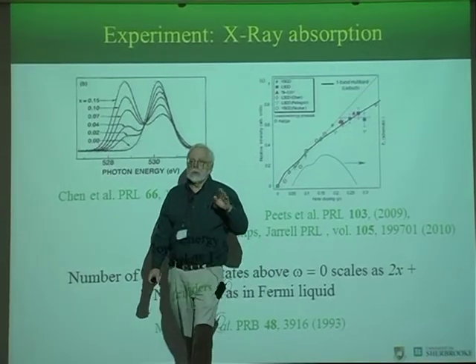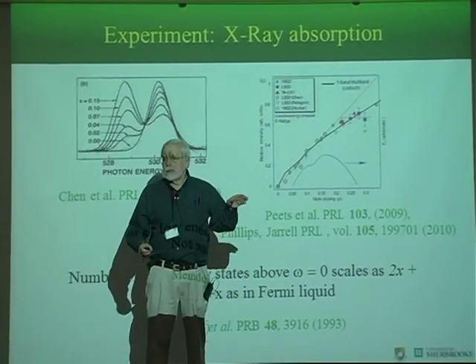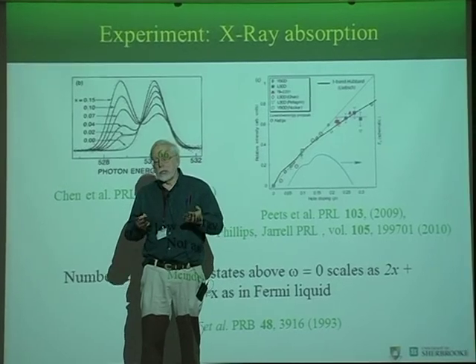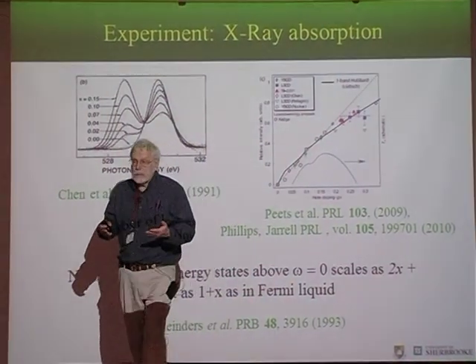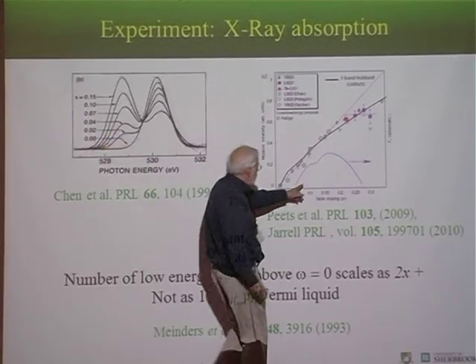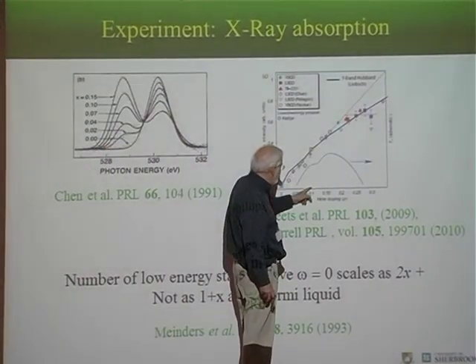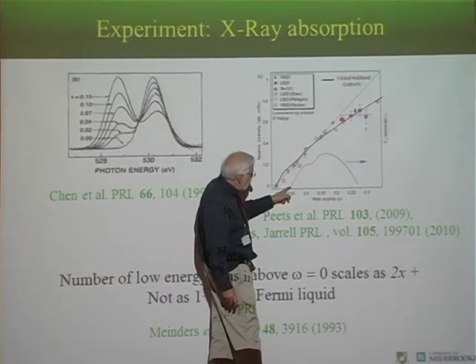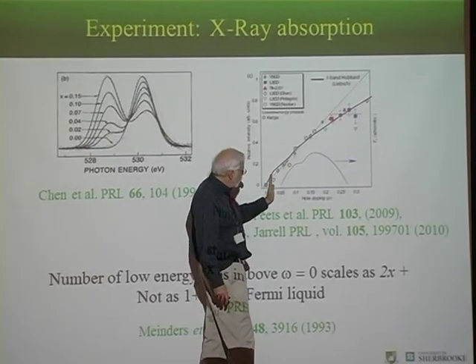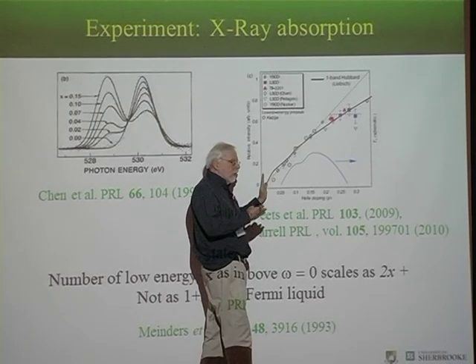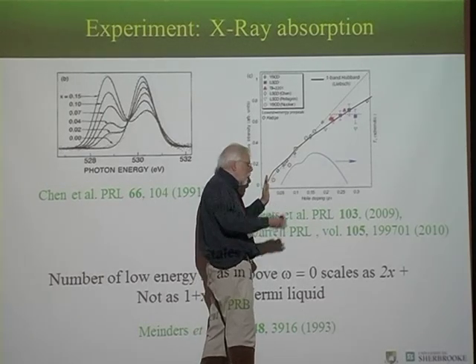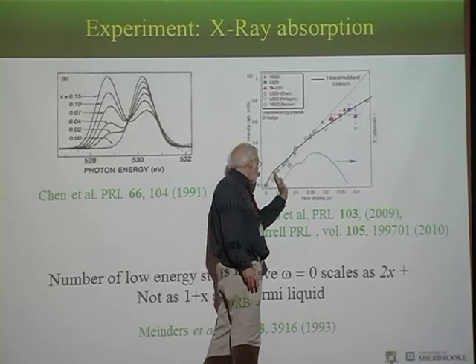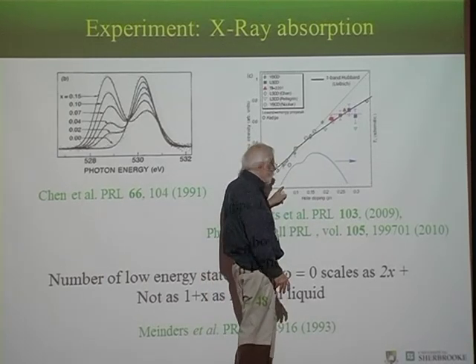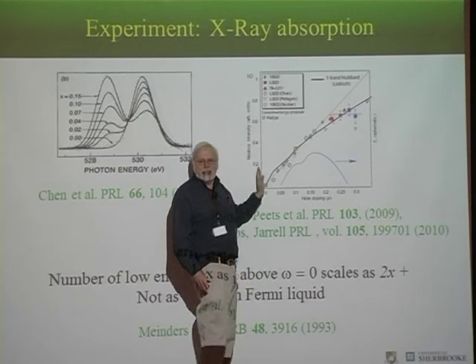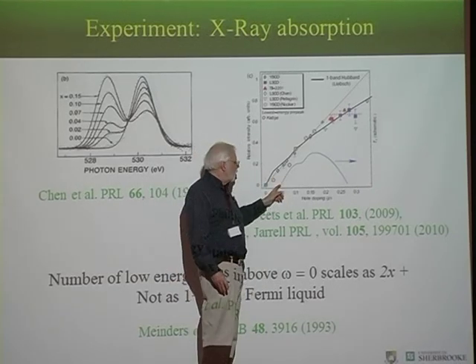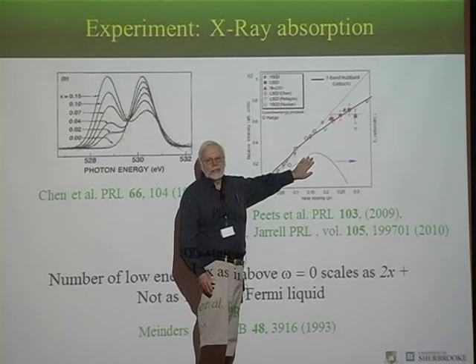So in LSCO, you don't see that dip, but in that case the charge density wave is stripes. When I say stripe, I mean charge and spin density wave sort of together. So there are stripes here, and then they just change direction when you get from here to there. I forget which direction it is. So they start right from here, and there you don't see this dip.